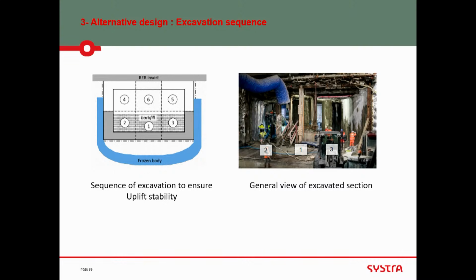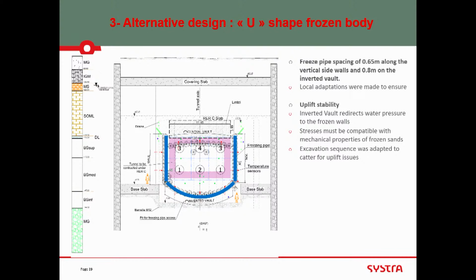There was another issue, which was uplift stability. For uplift stability, in fact, excavation was done sequentially. So gallery number 1, the lower gallery, then it was backfilled, then galleries 2 and 3, backfilled, so that there was no uplift during construction. And I'm going fast now. And we see here a general view of the excavation. The freezing pipes were at 80 centimeters and 65 centimeters.